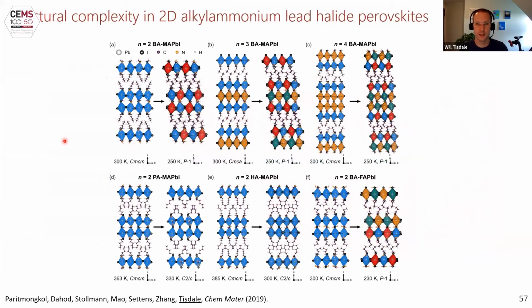We synthesized a large family of different thickness, multi-layered lead iodide perovskites. We solved their crystal structures. We did single crystal X-ray diffraction as a function of temperature, and mapped out the full phase diagram of these different materials. This is quite a long, detailed paper that my student Oat worked for about 3 years on with the synthesis and the characterization of these materials.